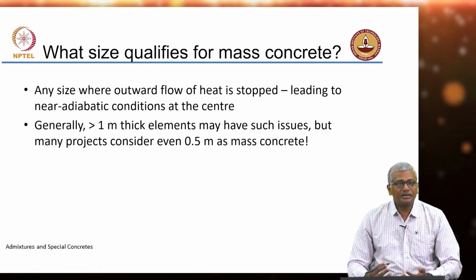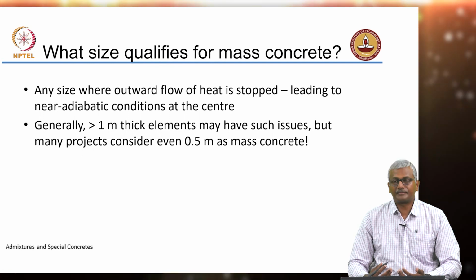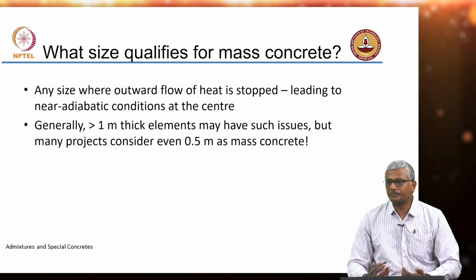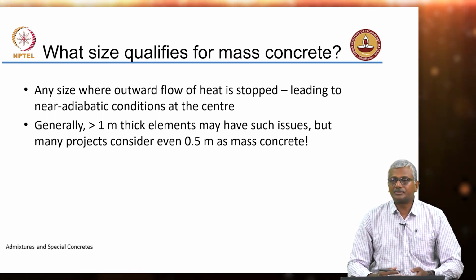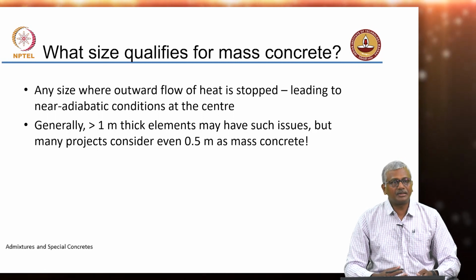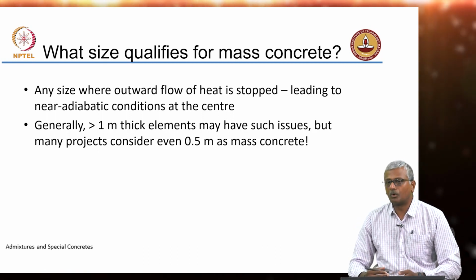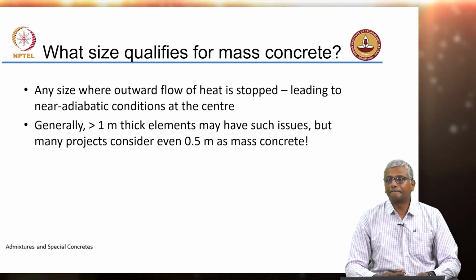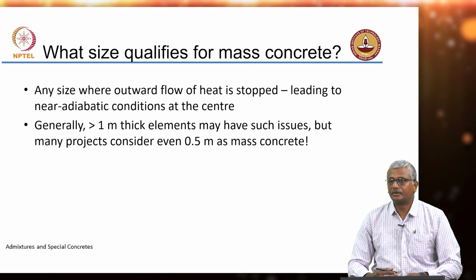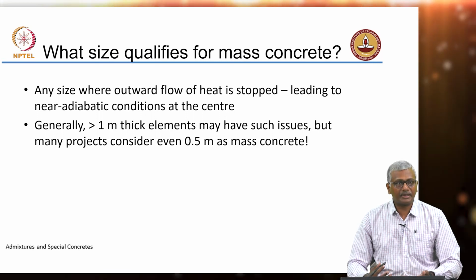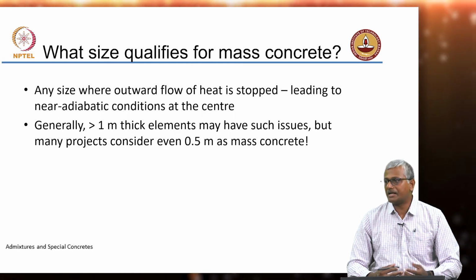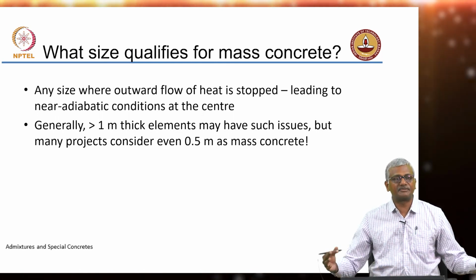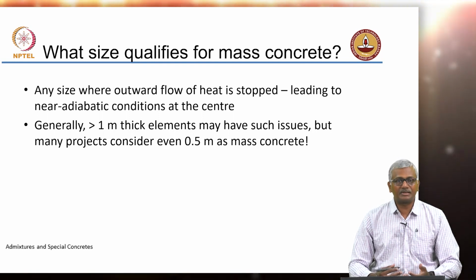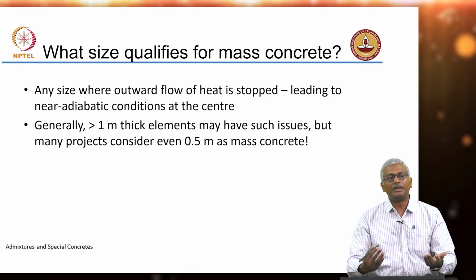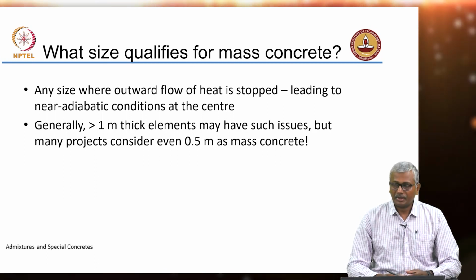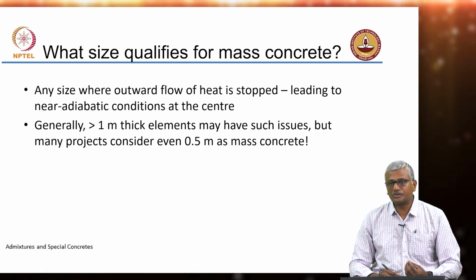Now, how do we define a particular size for mass concrete? What we have to look at is any structural member where the outward flow of heat is slow or is completely stopped, creating almost adiabatic conditions in the core of the concrete. What is adiabatic again? Yeah, essentially there is no outward or inward flow of heat from the system. So, that is called an adiabatic system. So, when the concrete has a massive size, the core will be almost in an adiabatic condition. That means the heat is not able to go out and no additional heat is able to come into this concrete. Generally, this will happen when elements are at least 1 meter thick.